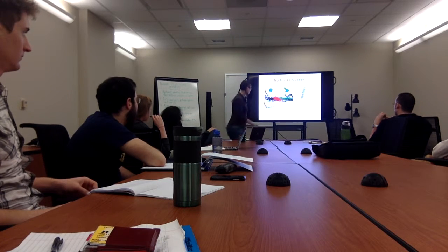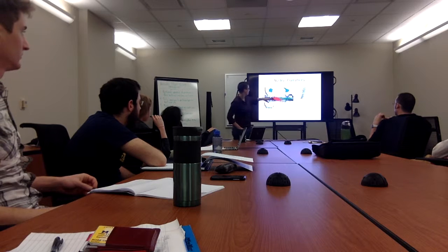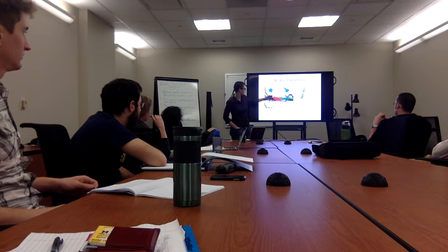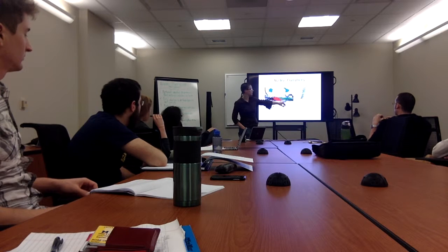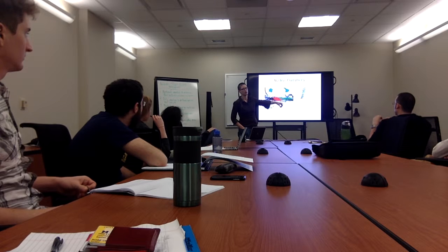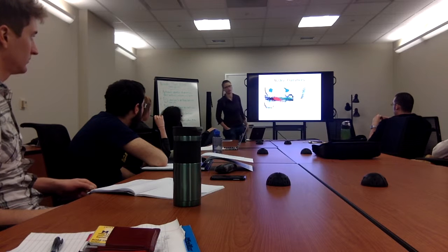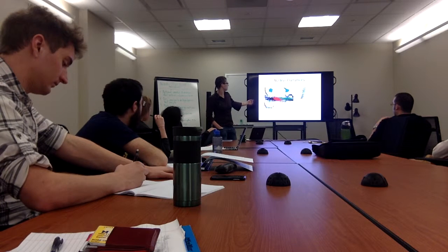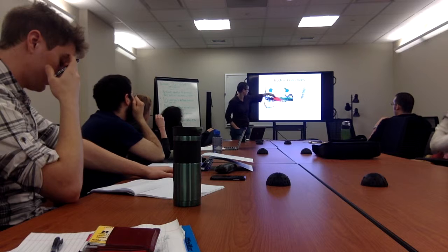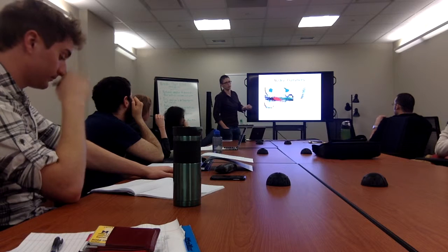This is a pretty interesting plot that shows the crystallinity on the inside of the cluster against cluster size, and these are isoenergy lines on here. What this is showing is that the nuclei that have roughly a 50% chance of forming, some of them are really large, but the ones that are really large can have a relatively low crystallinity. The ones that are smaller can be small, compact structures that are a lot more stable. And that's not explicitly said in here, but what's shown by the isoenergy plots too is that these actually have a lower free energy, the free energy difference is greater, because the crystal is better.